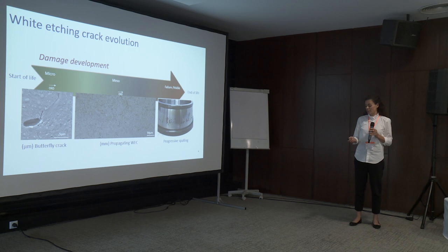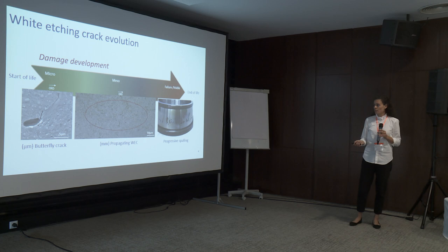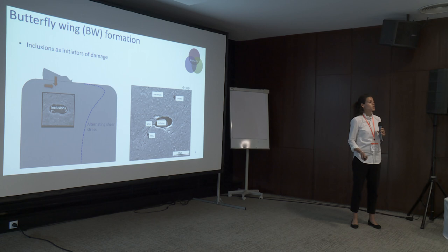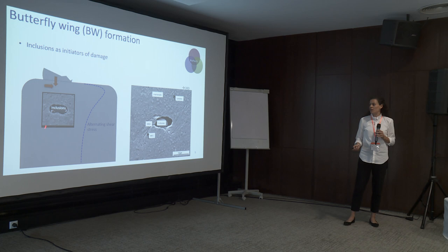Focusing on butterfly wing formation: as we have contact between the roller and the inner bearing, the subsurface stresses are highest somewhere up to one millimeter, depending on the contact pressure. If non-metallic inclusions are present in the martensitic matrix — a very hard and brittle material — cracks form, usually in a 45-degree orientation.